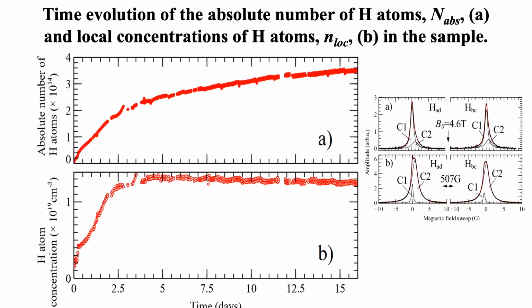After that, we study the behavior of the signal from hydrogen atoms. First, this is the total number concentration on time, shown here. And here is the dependence of the local concentration on time. You see that after 2.5 days it's saturated, and after that the local concentration doesn't change.